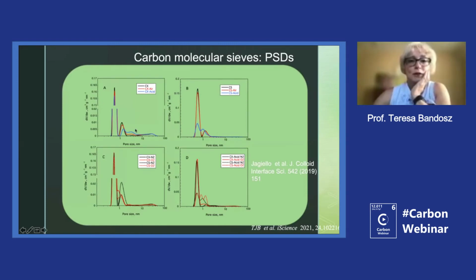Even looking at those distributions, it looks like Carboxen is more stable than Carbosieve. When we oxidized with air, really not too much happened, but oxidation with acid definitely decreased the volume of the pores. Also, the sizes are similar to before. And since for us oxygen adsorption and the interaction of oxygen with the small pores is important, we decided to also measure adsorption of oxygen on those carbons. That analysis was done by Jacek Jagiello, and we compared the distributions from oxygen and nitrogen.